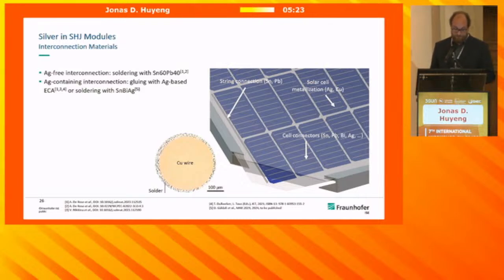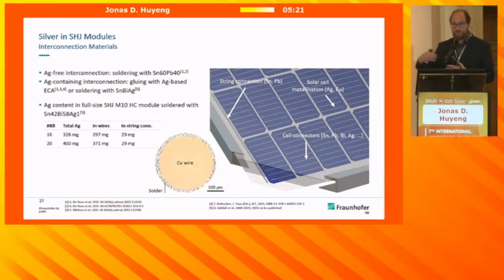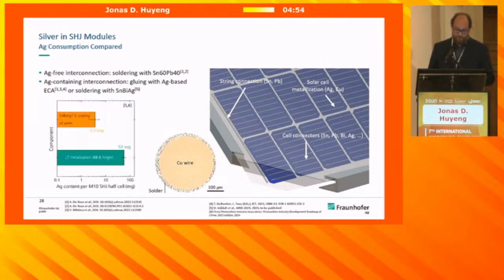tin bismuth silver alloy. And then if you sum all these wires up, and because people like putting more wires on their cells, you can see that you're already entering a range of 300 to 400 milligrams per M10 module. You can deduct about 10% if you are clever enough to do your string interconnection not with a silver-containing solder. But yeah, this is already some silver consumption that you have. How does it compare to the metallization part? Of course, the metallization part is still very dominating. This is a logarithmic scale, so there's a lot more in the busbar than finger metallization.